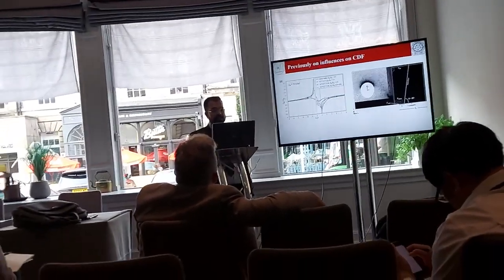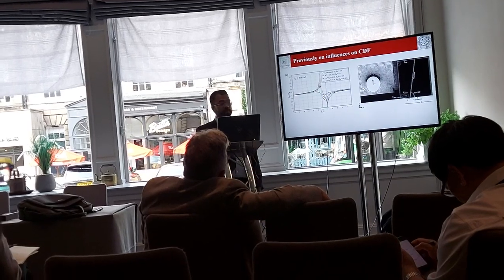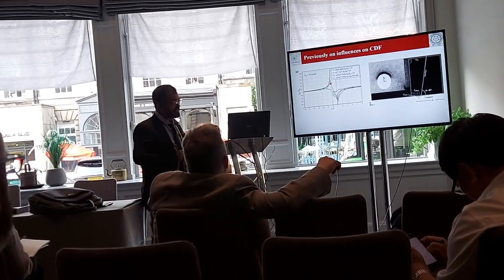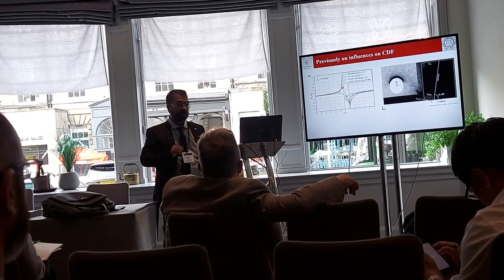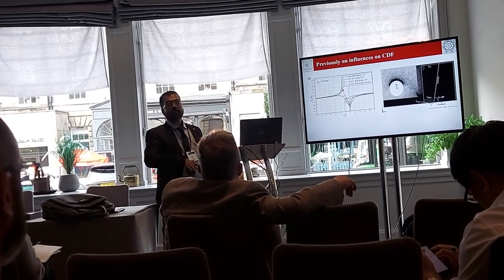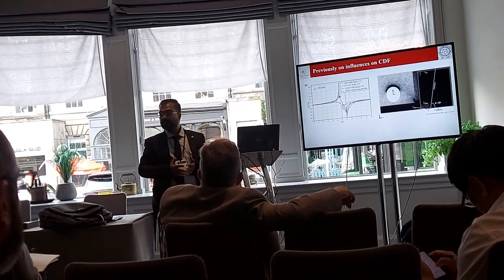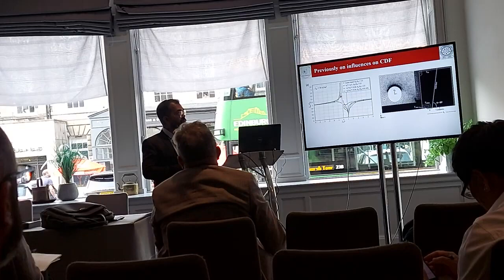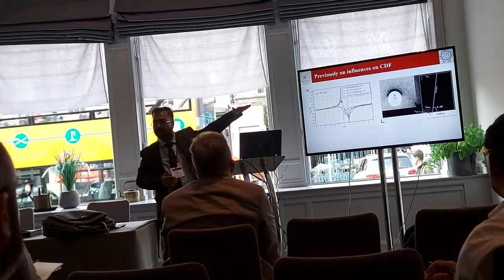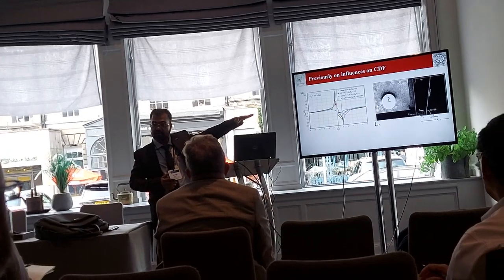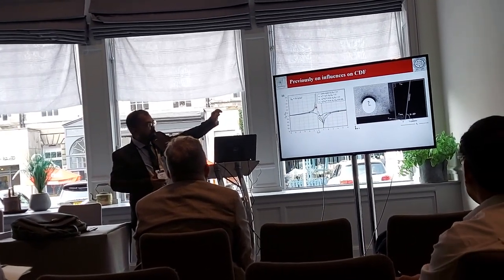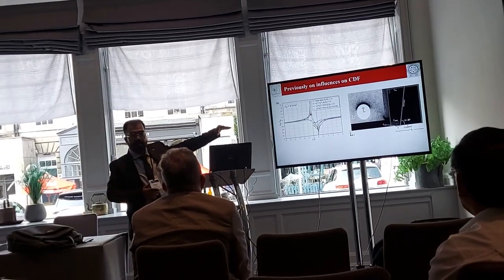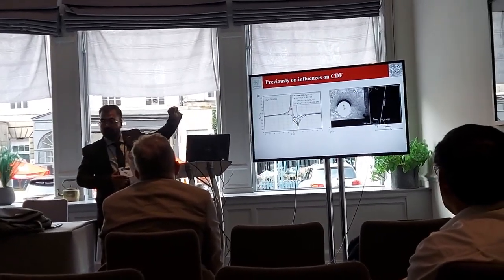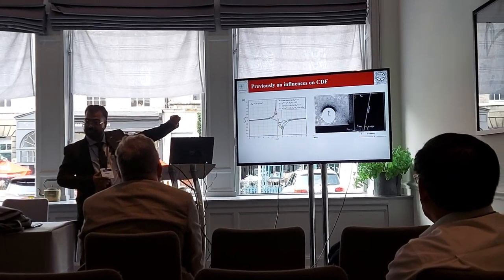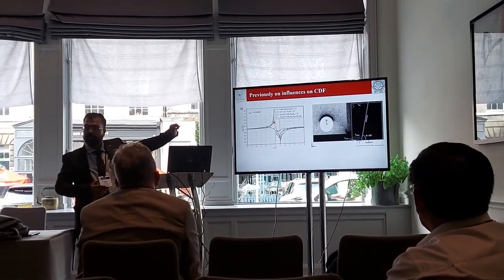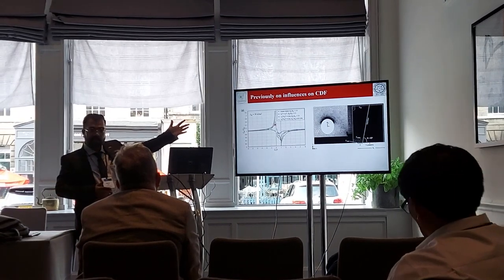You see that the linear elastic calculation shows a different result, so let me explain this. J integral is path independent, and we'll talk about that. That would be the case if it was a homogeneous material. If it is a homogeneous material, then it will be a horizontal line at 1, so J tip will be equal to J far, because that will be path independent. But in the presence of a different material, what is happening? Each point on this plot is one model at a different crack tip location. The same result can also be obtained if you incorporate a damage model in finite element analysis.